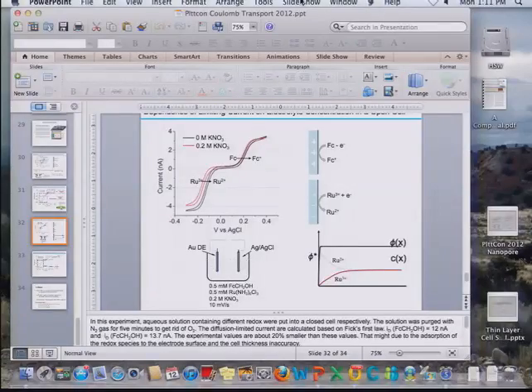Likewise, if you put ferrocene in and look at the oxidation of ferrocene, and you put in ruthenium hexaammine and look at the reduction, this again is at a gold disc electrode. What you see is when you take the electrolyte out, there's no effect on the oxidation of a neutral molecule, because it doesn't care if there's any excess charge at the electrode surface. But the ruthenium reduction is enhanced because, when I go from 3+ to 2+, that's equivalent to creating a negative charge at the surface, and that enhances the migrational flux of the ruthenium-3.